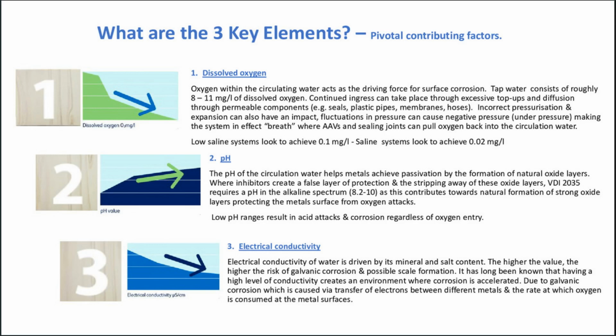If we look at the pH of circulating water, it helps achieve passivation by the formation of natural oxide layers, where inhibitors create a false layer of protection and strip away these oxide layers. VDI 2035 requires a pH in the alkaline spectrum, so that's 8.2 to 10, depending on what your system metals are, as this contributes to the natural formation of strong oxide layer protection, protecting the metal surfaces from oxygen attacks. So low pH ranges result in acid attacks and corrosion regardless of oxygen entry.